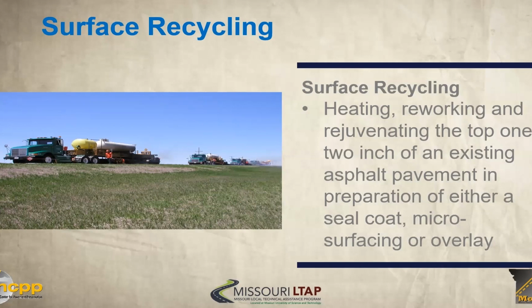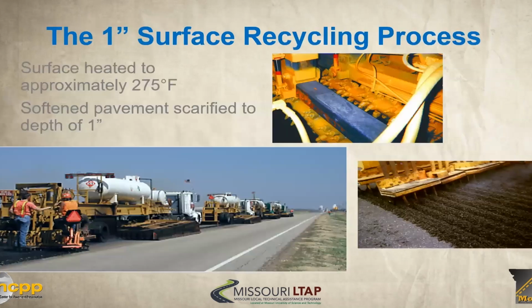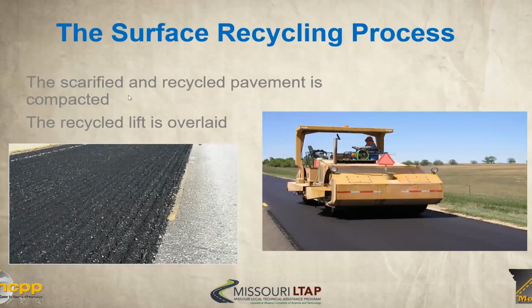you're using. So with surface recycling, you can see here, we're really focusing on heating, reworking, and rejuvenating that top 1 to 2 inches of an existing pavement. And we might be doing that in preparation of something else, or it could be that we're leaving it as such as the riding surface, depending on traffic levels. And so for that process, just a brief introduction. You want to heat the pavement to about 275 degrees, and then basically you're going to try to scarify the material, the heated material, to a depth of about 1 inch. And then that scarified material is then compacted. The recycled lift is overlaid.